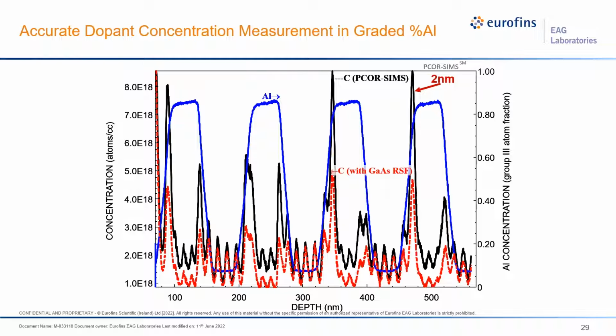But before we go on, this slide points to the importance of using our PCOR-SIMS corrections to carbon sensitivity. You can see how using only gallium arsenide sensitivities, that's the red curve, the carbon doping spikes at the interfaces would be underreported by a factor of 2 compared to the PCOR-SIMS profiles, that's the black curve. The slide also demonstrates the ability to resolve these spikes even though they are only 2 nanometers thick. But for a more detailed look at the P-DBR region, let's look at a higher depth resolution analysis of the top of that DBR.